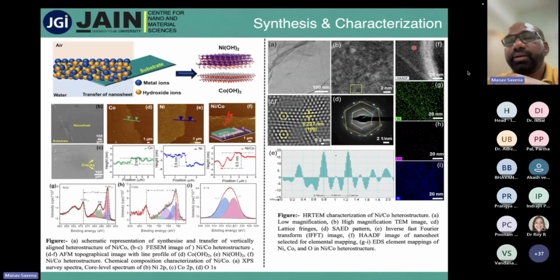Here we can see the TEM analysis in figure A. We can see the large area, we can see the wrinkles, which shows the flexibility of the sheet, and the crystalline domain size, which is around 2 nanometer. So there are a lot of domains present there. At present, all domains are not aligned in one direction, so it is a polycrystalline type of film. We are trying to achieve a film where all the domains are aligned in a particular direction, so we can get much more exciting properties.